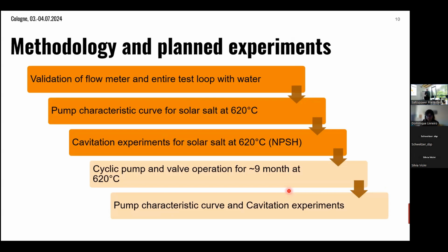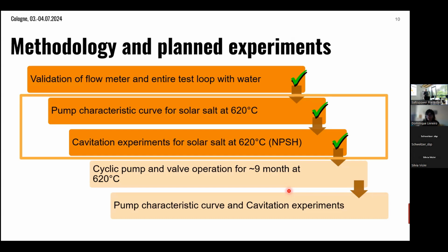Here is the methodology for the planned experiments. First, we have a validation of the flow meter and the entire test loop with water. Also, the pump was tested with water before it was shipped to the DLR. We then did the pump characteristic curves with molten salt at 620 degrees at the DLR, and also the cavitation experiments for molten salt. And that's what I will talk about now. After this, there will follow a period of 6 to 9 months cyclic pump and valve operation up to 620 degrees. And again, to see if there are changes in the characteristic curves and cavitation, we'll do these experiments again.